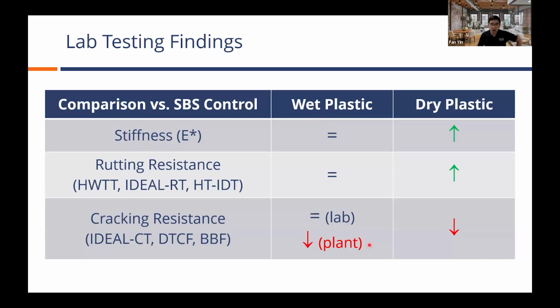The only difference we saw is that when we look at the plant-produced mixes, the wet plastic mix did not perform as well as the SBS control mix when we look at IDEAL-CT, AMPT cyclic fatigue, or bending beam. That was a little bit different from what we saw in the lab results, and I think that could be something related to the production variability that caused a little bit of variation. But overall, we have been very pleased with the wet process formulation that we came up with by working with Dow Chemicals.